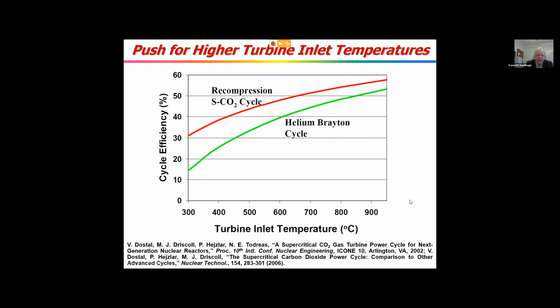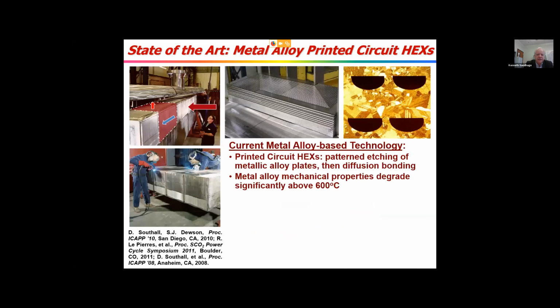Currently, CSP plants operate at highest temperatures around 550 or so centigrade. We'd love to get up to 750, 800 or higher to get a dramatic increase in electricity efficiency production and lower effective levelized cost of electricity. So one of the challenges in doing that is the heat exchanger. A very effective type of heat exchanger, compact heat exchanger, is called a printed circuit heat exchanger. They're currently made out of metal alloys like stainless steels, and you can see some of the photographs of this type of heat exchanger. They're very thin sheets of metal that have been patterned into channel patterns, as you see on the upper right there, typically by a chemical etching process, which itself is kind of slow and somewhat expensive.